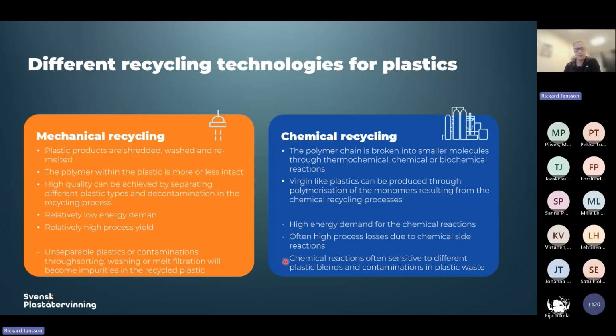And even if they are often marketed as a very good recycling for mixed plastics and plastic waste, in reality, what we see is that they are often sensitive to different plastic blends and contaminations within the plastic waste, because if you have heteroatoms such as nitrogen or oxygen from polymers that are not purely hydrocarbon based, so the purely hydrocarbon based polymers are, for example, polypropylene, polyethylene, and polystyrene. But if you have polyamide or PET, you would bring nitrogen or oxygen also into the process, and these heteroatoms are going to form very low value chemical reaction products in the thermochemical reaction pathways.